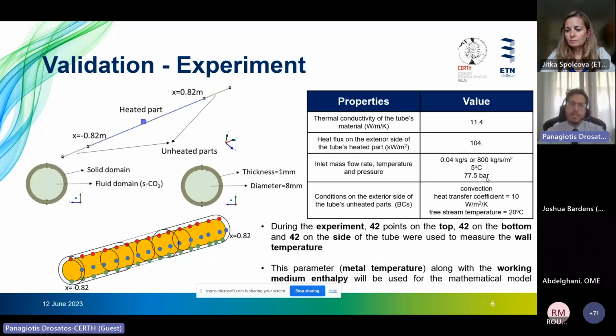The first step, as I mentioned, is the validation study. Here, we use experimental data regarding the thermal stratification phenomena of a supercritical CO2 flow inside horizontal heated pipes. In order to evaluate the results, we utilize the developed temperature field on the top, bottom, and side of the horizontal pipes versus the working medium enthalpy.